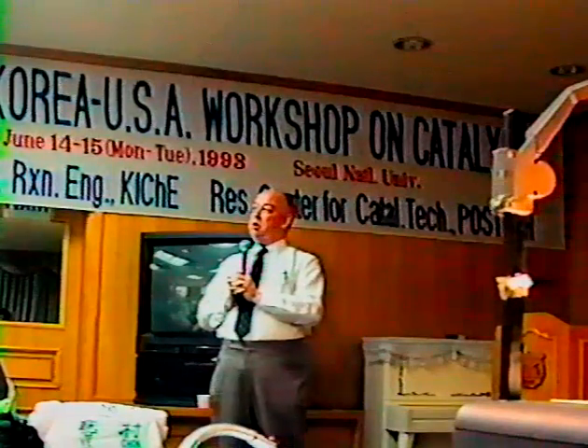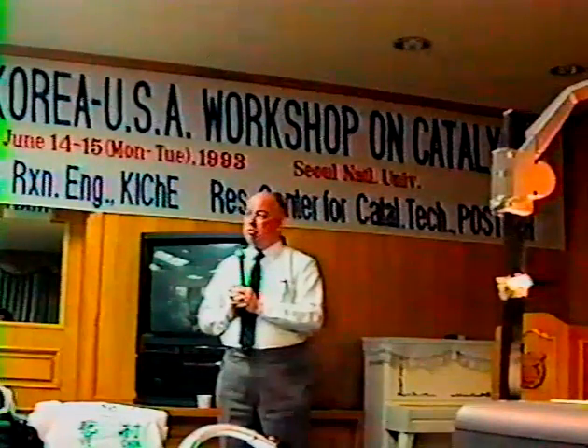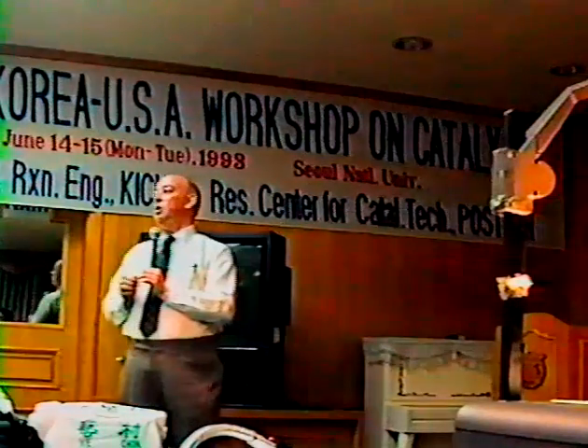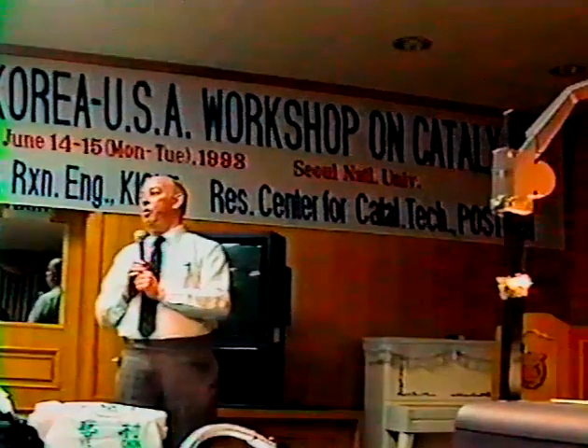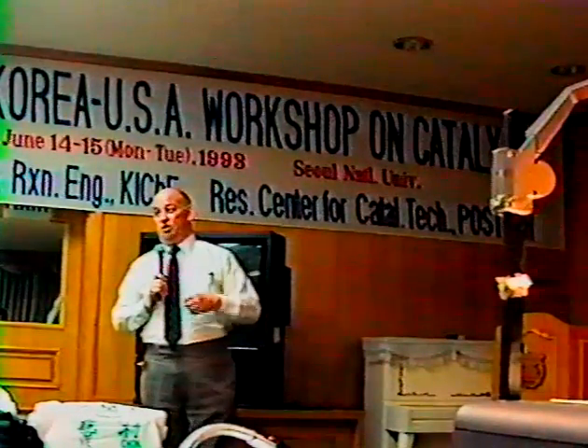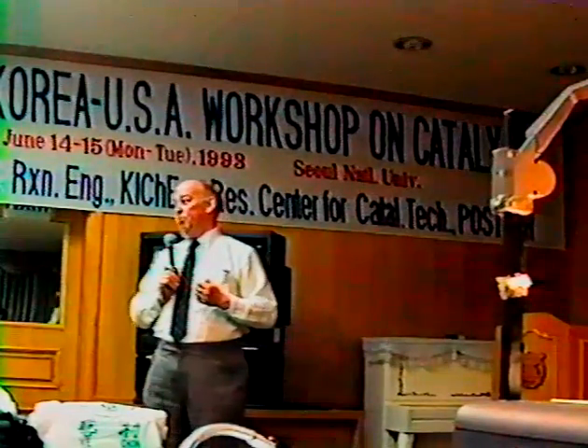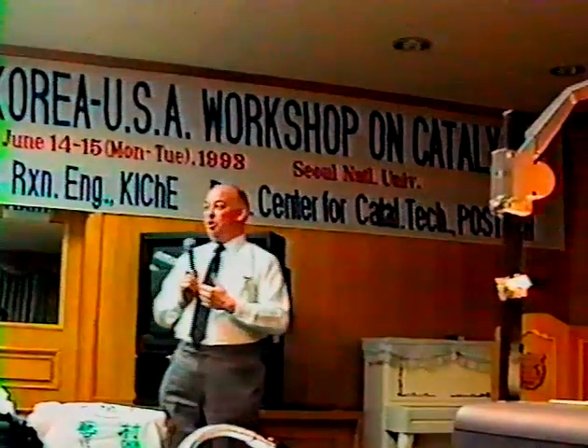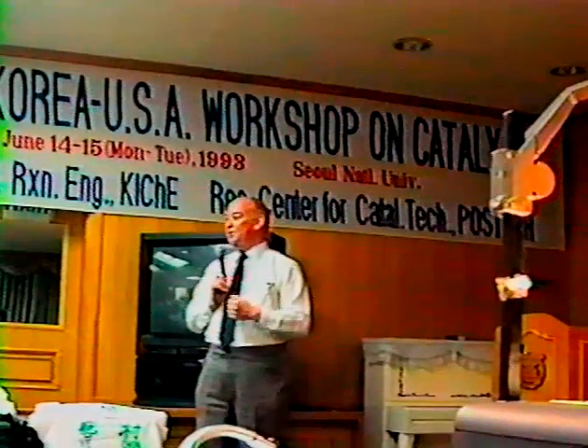Did you check the operating point and the pressure and temperature range? Did you make some range of the temperature and pressure? Did you check that? We checked it from the activity point of view. Yeah. We did not do gravimetric absorption experiments. I threw this data out, and somebody in the academic world might be interested in finding out what this phenomenon is. We really don't have time to do it. We found a solution to it, so we moved on. The solution was to treat the catalyst with some oxygen. Okay.